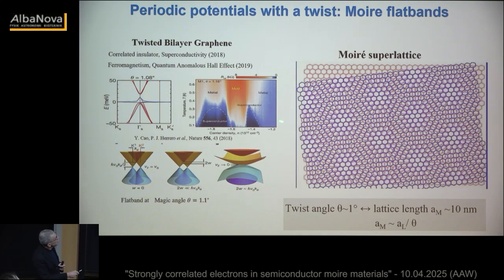Here it's only holes, but you can do it for both electrons and holes. You can move the chemical potential up or down from the charge neutrality point. And what you see is that you go from insulating states to superconducting states, etc. So almost exactly the same kind of phenomenology or phases that you observe in cuprates. All right, so this was the first story in 2018.